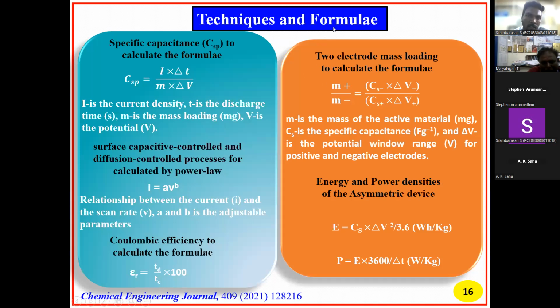Next, the techniques and formulas. The specific capacitance is calculated using the formula I times delta T divided by M times delta V. Next, the surface capacitive controlled and diffusion controlled processes are calculated by the power law, so I is equal to A V power b. Then the Coulombic efficiency, eta, is equal to the discharge time divided by the charge time, times 100.